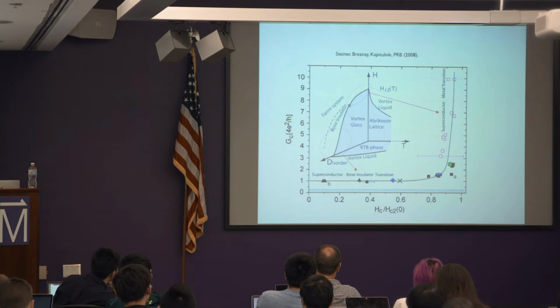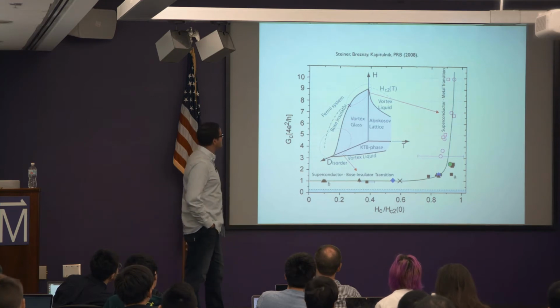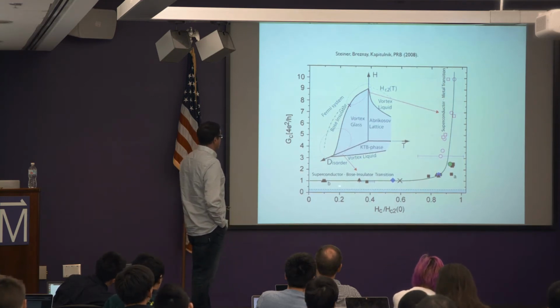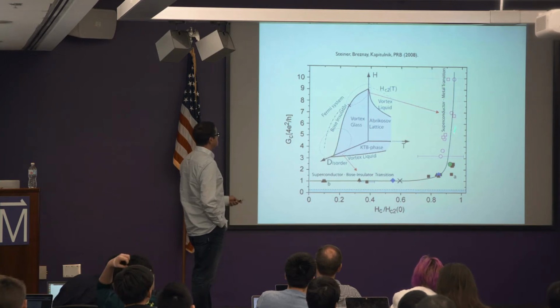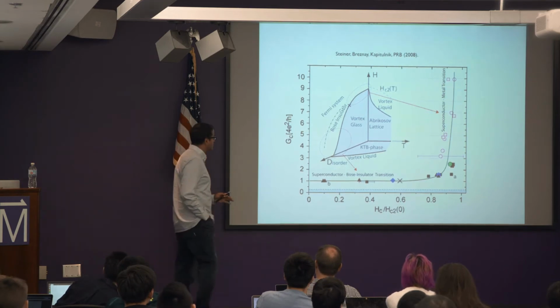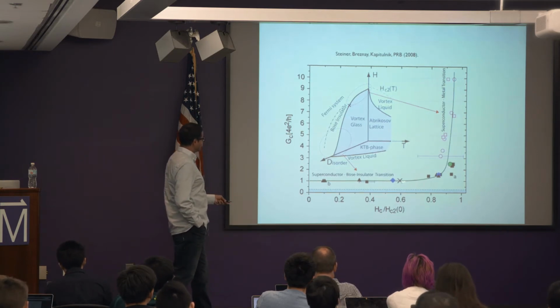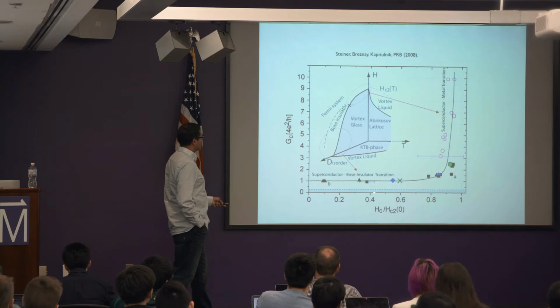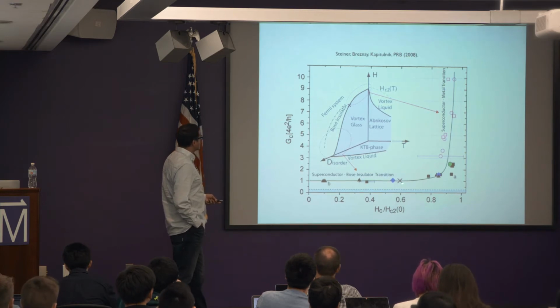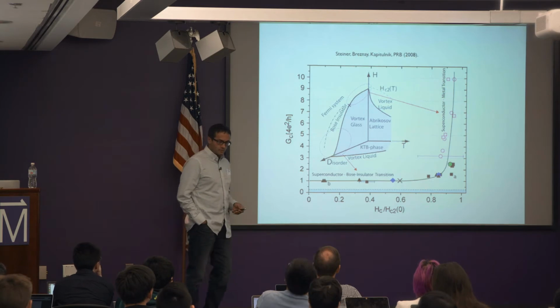Yeah. Okay, so now to address this point about how universal is the quote-unquote universal resistance for the field-tuned superconductor to insulator transition. Okay, so what you are seeing here are data from many different types of materials that undergo the superconductor insulator transition. What this HC2 represents is the magnetic field at which you lose the superconductivity. Okay? One set of materials undergo this superconductor to insulator transition where the critical conductance is 4e squared over h, so the critical resistance would be h over 4e squared.